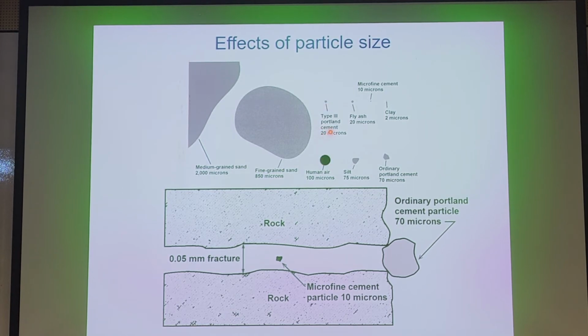And these are different types of binders that we can use. This is type 3 Portland cement, there's type 1, 2, 3. Compositions are more or less the same. Fly ash is another type of binder we use. These are just byproducts from industrial processes. We have microfine cement. Microfine cement may be very good for getting into very impervious soils. Then you have clay here. It's 2 microns. So by looking at this, you can probably guess it's very difficult to permeate grout into clay, given that microfine cement is 10 microns, and a clay particle is 2 microns.